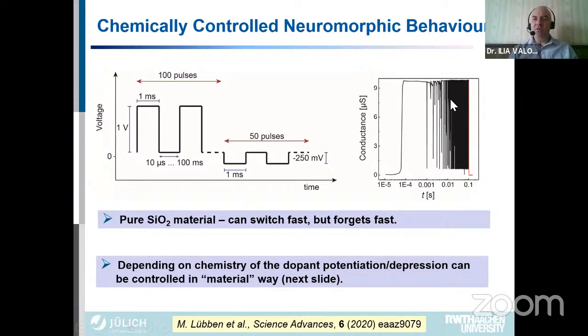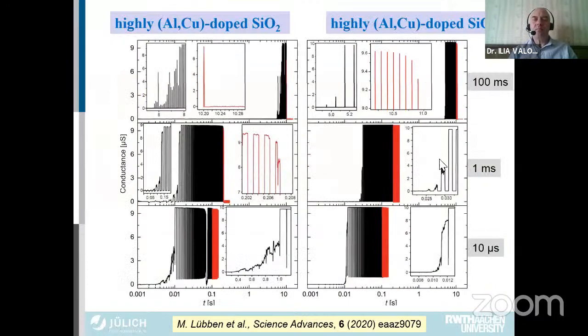With a very pure material, very pure silicon oxide, you see a very fast switching because the material is very fast. It's not providing any problems for copper ions to diffuse, but the filament is also very unstable at this current compliance. At low current compliance, it's immediately switching off. So fast switching, but unstable filaments. On the other hand, when you use dopants, for copper and aluminum, sorry, I have put both aluminum and copper, you see a different time for switching, but also a different time for depression, for reset, for forgetting, so to say.